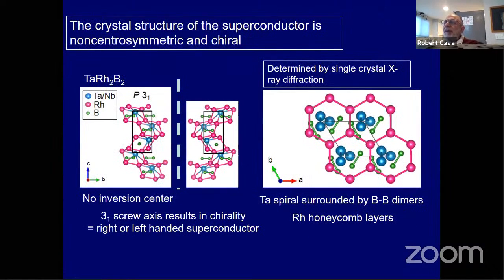And there was a lovely surprise about this, which Weiwei figured out, which is that they are non-centrosymmetric and they are chiral non-centrosymmetric, meaning that not only do they have no center of symmetry, but they have a handedness. And what I realized in looking back at the literature on superconductivity is that although it was appreciated that non-centrosymmetry was significant, the fact that there was chirality was not really appreciated. So if you look at it, there's a honeycomb lattice of one set of atoms. There's boron dumbbells, which are cool for chemistry. And then there's these things here, which are spirals of the tantalum.